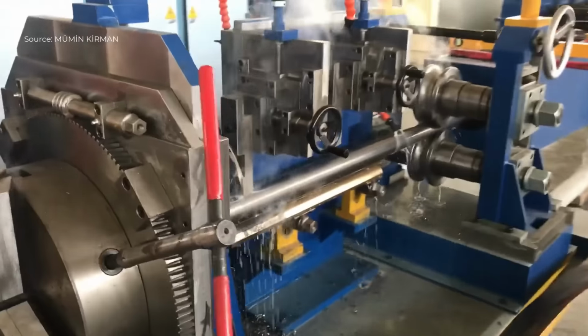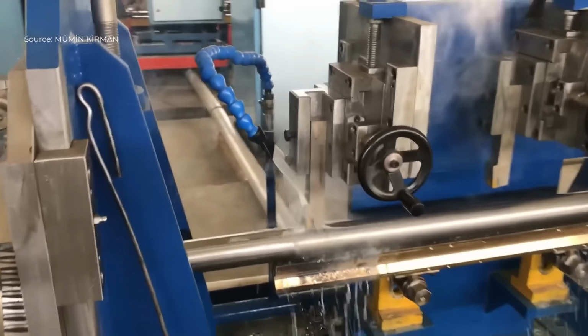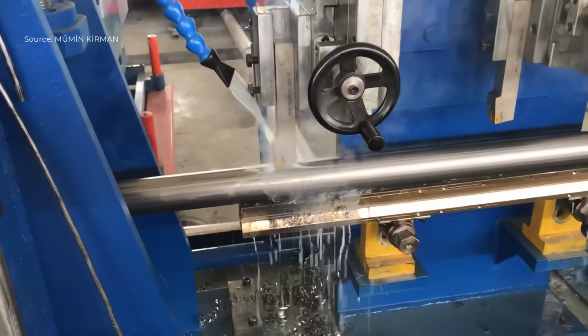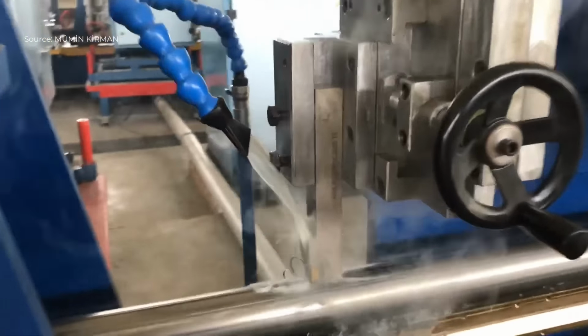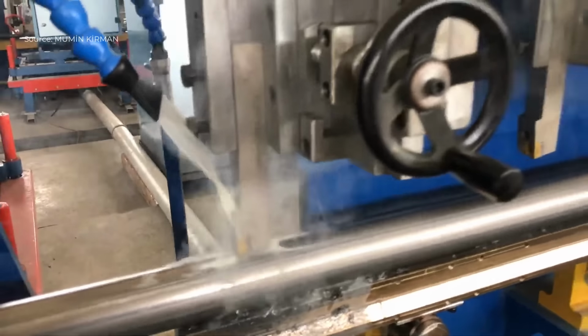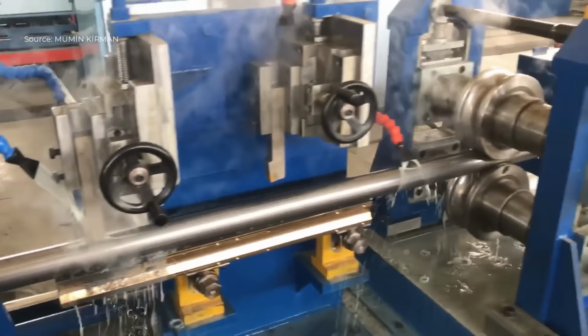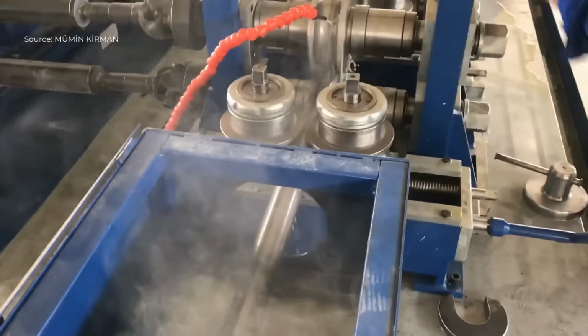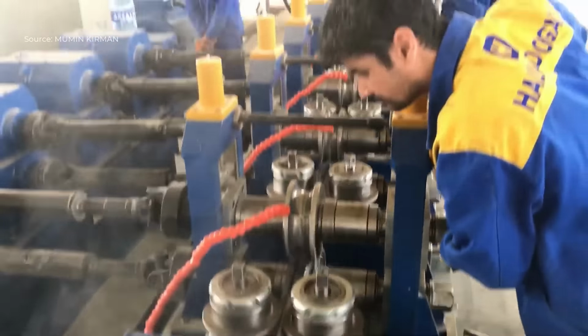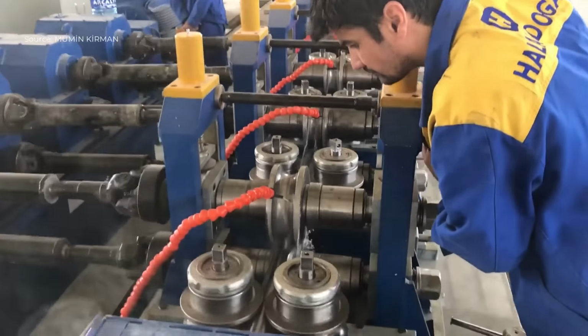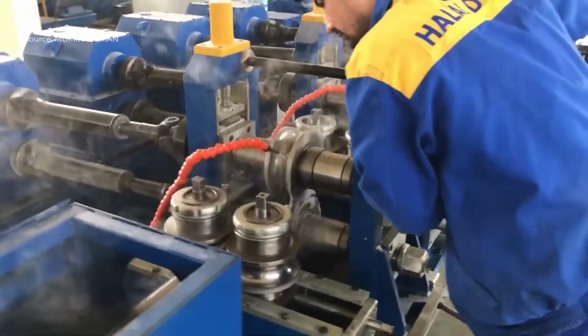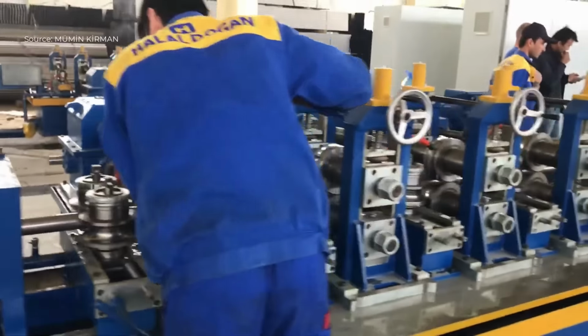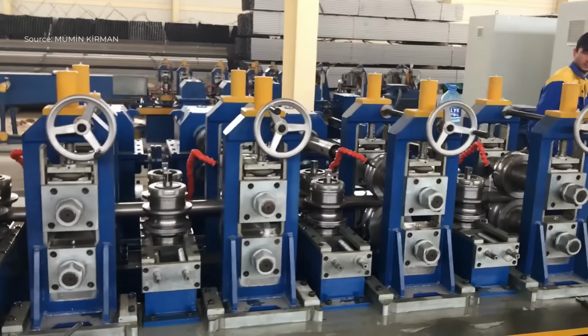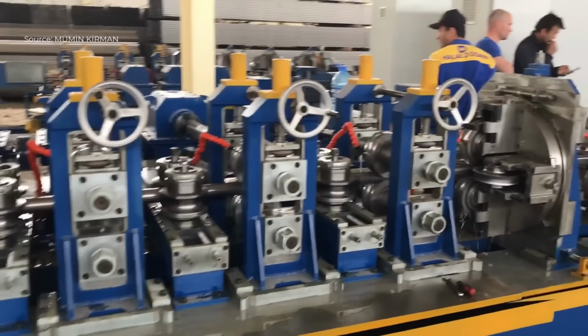The welded round tube then moves into the sizing and reshaping section. In this stage, specially designed rollers progressively transform the round tube into a square profile. Each stand carefully controls the deformation, forming sharp and consistent corners, while maintaining uniform wall thickness and dimensional accuracy. Fine adjustment of the rollers ensures that the square tube meets strict tolerance requirements.